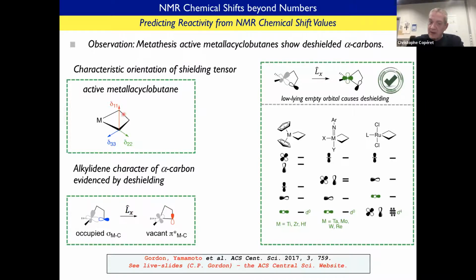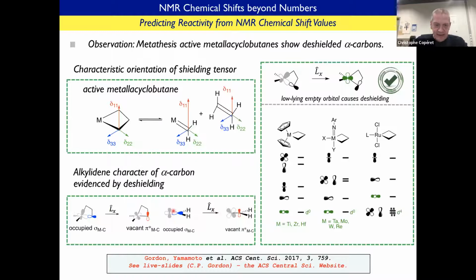to explain this very large deshielding value. And in fact, if you look very carefully at this molecular orbital representation of a metal-carbon bond in a metallacyclobutane that is active in metathesis, they are very much related to the corresponding metal-carbon bonding orbital that you would imply in the corresponding alkylidene, which has to react with olefin to make this metallacyclobutane. Basically, what this scheme is telling you is that all the metallacyclobutanes that carry out metathesis, whether with titanium, molybdenum, tungsten, or ruthenium, which are very different classes of catalysts, obey the same rule of symmetry.